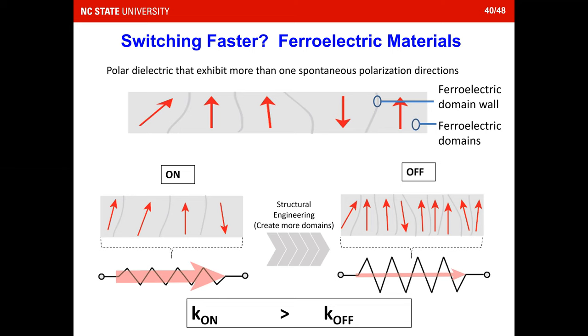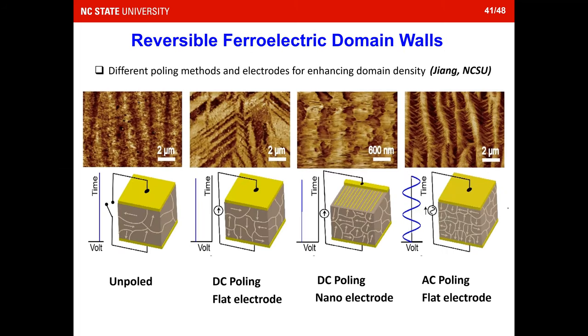Within the same polarization, you have something called ferroelectric domains, and in between those domains, you have domain walls. By applying the electric field, you can actually control the density of those domain walls. So hopefully, by this kind of electrical switching, on demand, you can control the density of the domains so that you can control the thermal conductivity. This would really be a fast thermal switch, we hope. Dr. Jiang provided a lot of preliminary data on how you can switch those domain densities, and it's pretty good because that's what we need. We need reversible ferroelectric domain wall switches.